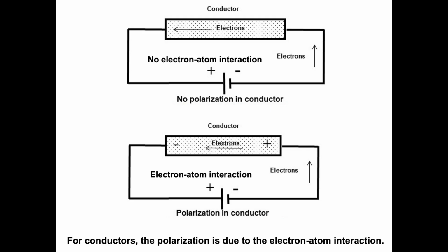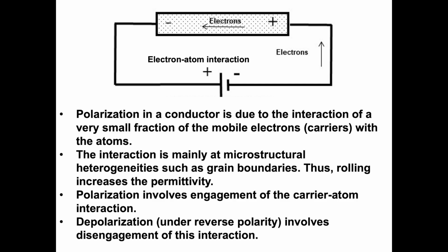If there is no electron-atom interaction, then the electrons just loop around the circuit and no polarization occurs. But if a small fraction of the mobile electrons interact with the atoms, then you can have polarization. And that is the mechanism which we found to be indeed the case, the electron-atom interaction. And this interaction we further found to be mainly occurring at the microstructural heterogeneities, such as grain boundaries. And so mechanical rolling, for instance, would increase the permittivity because it refines the microstructure.